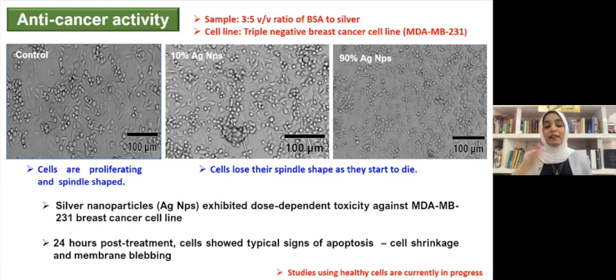When we added the several concentrations of our silver nanoparticles, we observed that they actually lost the spindle shape and they started to die. So here we concluded that the silver nanoparticles showed dose-dependent toxicity against this particular breast cancer cell line. After 24 hours after the treatment, we came back and saw that the cells showed typical signs of apoptosis like cell shrinkage and membrane blebbing. Studies using healthy cells are also in progress currently. Can I have the next slide, please?